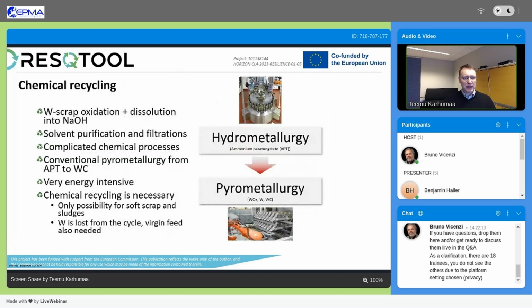If we look at the chemical recycling, the picture comes much more complicated. So hard metal scrap or tungsten scrap that goes to chemical recycling needs two different types of processes. Firstly, hydrometallurgical process to purify the materials, and then pyrometallurgical processes to define the grain size of the material, plus create tungsten carbide from the tungsten oxides or ammonium paratungstate. That was the outcome of the hydrometallurgical processes. So there are multiple dissolution, purification, filtration steps. It's very complicated chemistry, and then